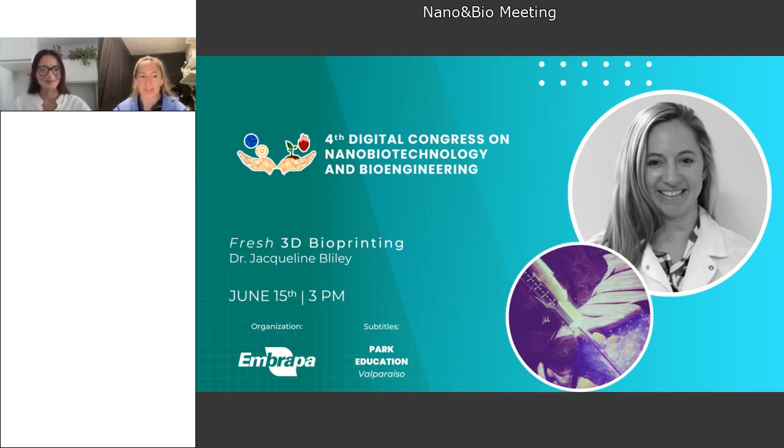No, that's great. I think the thing that FRESH really brings to the table is that we're able to reproduce very complex structures, not only with materials, but with cells, which is very difficult to do with soft materials. A lot of the field has relied on strengthening these materials either through UV cross-linking as it's being printed or using some sort of cross-linker during the printing process. We don't do that. We can print the materials and cells directly because we have the support bath that supports it while it's gelling, and then we can remove it. So we're able to reproduce very complex prints that are very difficult to produce from soft materials in general, which is very applicable to printing tissues and organs.